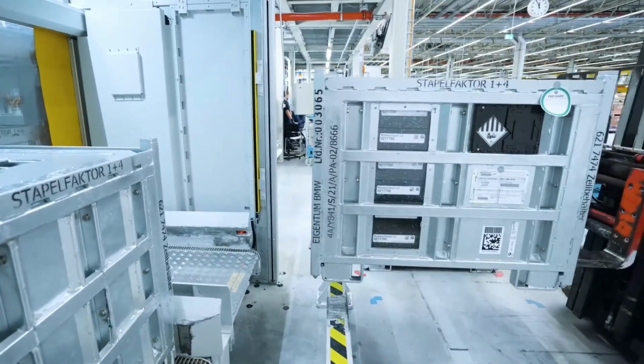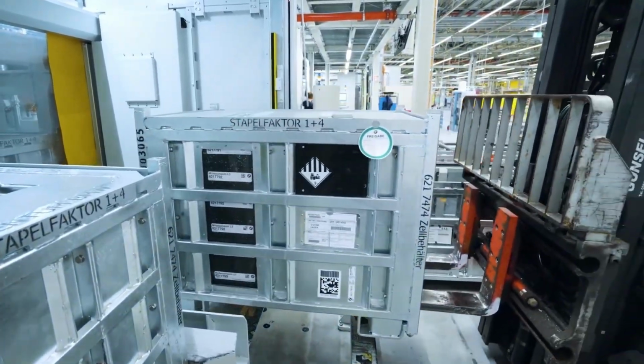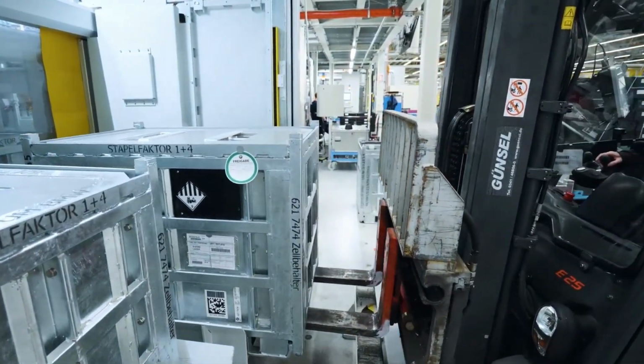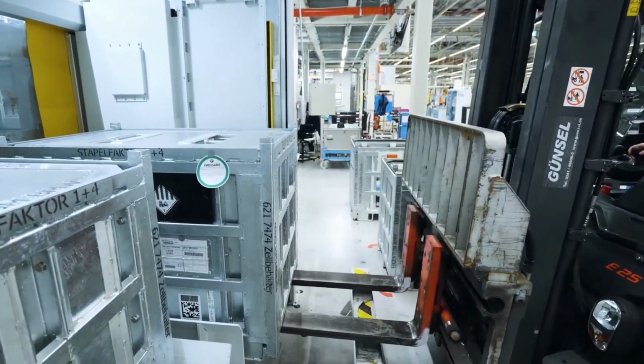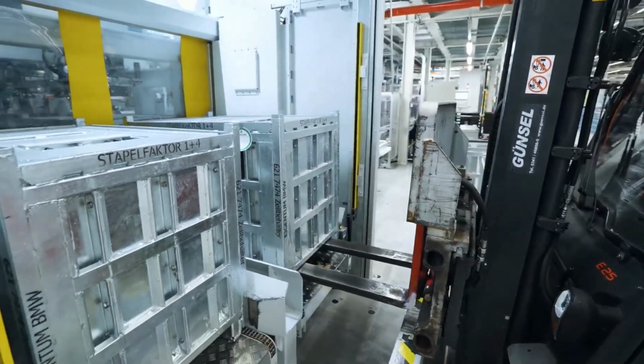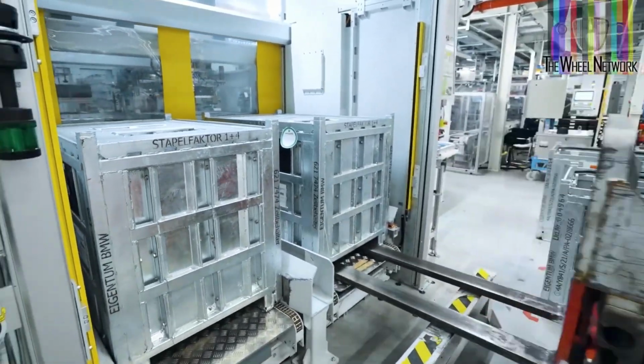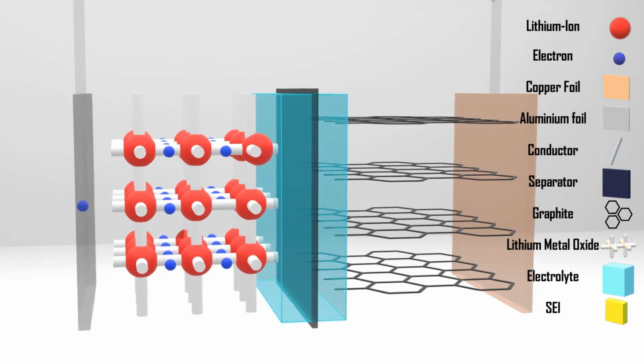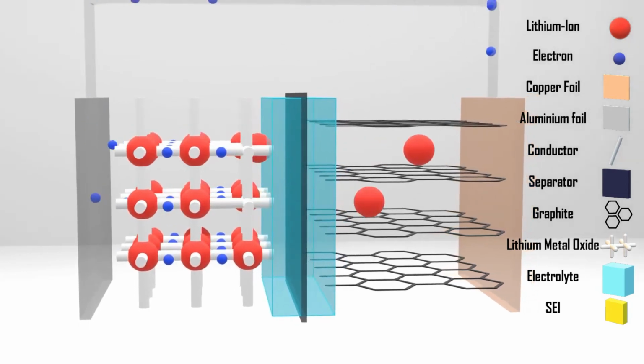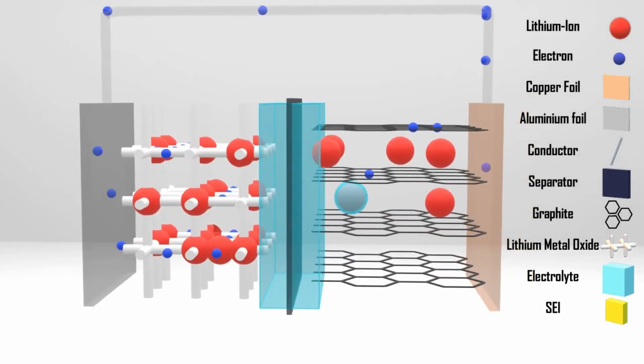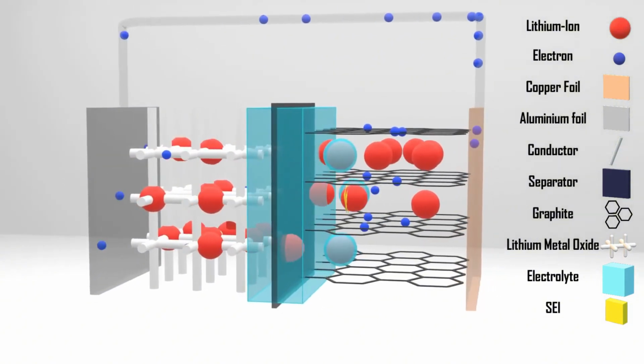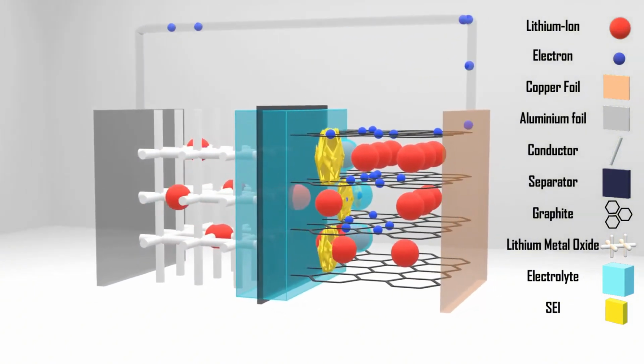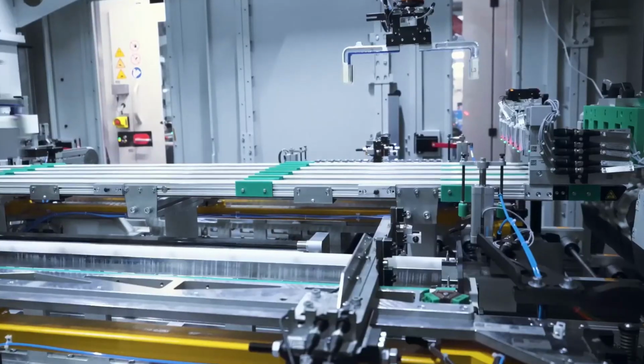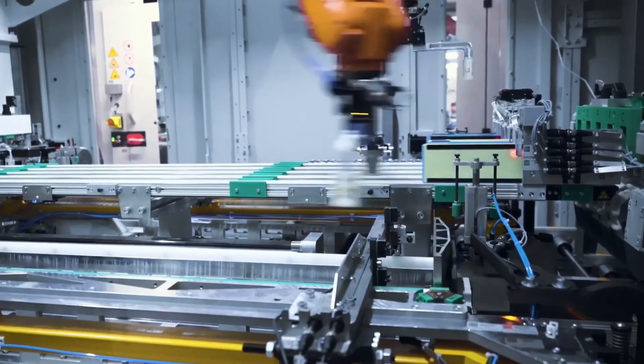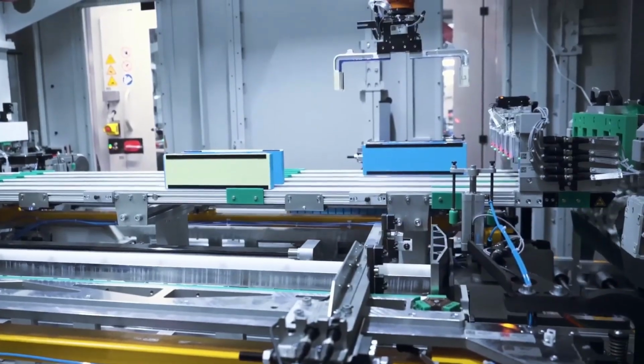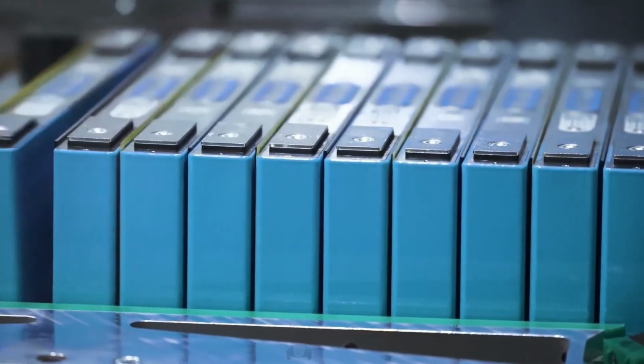Once the soaking is complete, the battery undergoes a forming process where it's charged for the first time. This step activates the chemical reactions within the battery and forms a solid electrolyte interface layer on the anode. The SEI layer is essential for the battery's long-term stability as it prevents further reactions between the electrolyte and the anode. However, forming is a delicate process that must be carefully controlled. Too much current can damage the SEI layer, while too little can result in an incomplete formation.